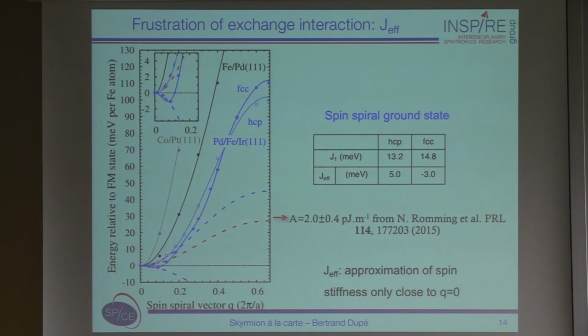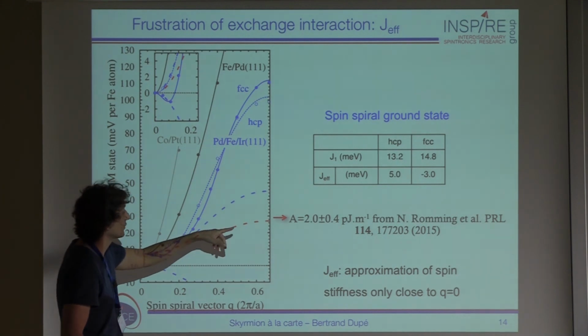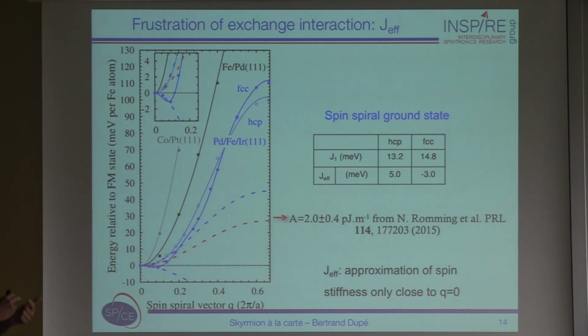And actually there was a paper of Niklas Romming in the group of Professor Wiesendanger who showed that he could fit a set of exchange interaction, anisotropy and DMI, and reproduce very well the 0 temperature phase diagram. So if you plot his coefficients here on top of the dispersion curve of this palladium, iron, iridium 111 system, this is what you get. This is the red curve here.